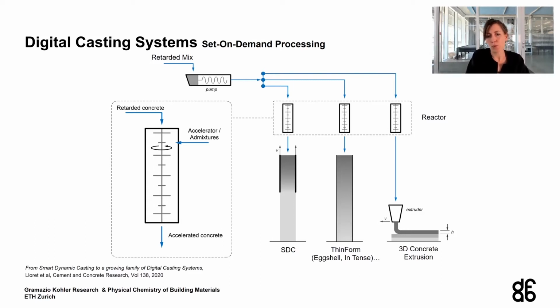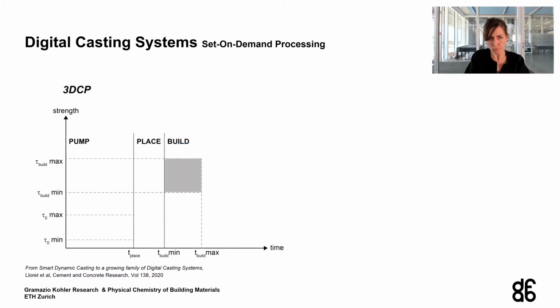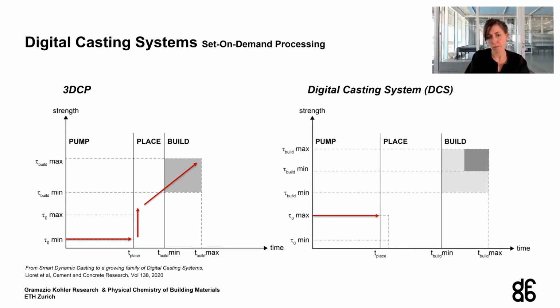It's very similar to what we do in 3D concrete extrusion, apart from the fact that we are using a self-compacting material that is placed into a minimal mold, whereas they print in a layer-by-layer manner. So if we look at 3D concrete printing, we need a material that is pumpable. Then it needs to immediately obtain strength to sustain its own weight and then sustain the next layers on top. For digital casting systems, we also need a pumpable material, but one that is self-compacting when placed into the mold, and then builds up strength to sustain the weight of the layers placed on top.